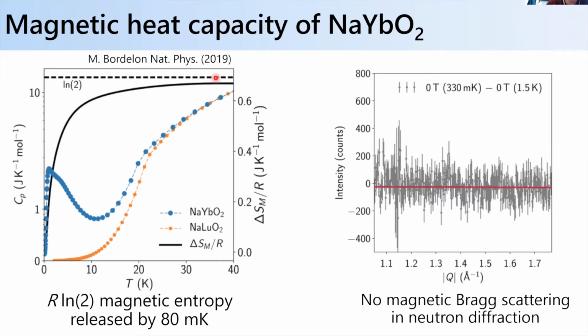So this tells you two things. First is that the J effective 1/2 model is correct in this temperature regime. And the second thing is that by the time you've gotten down to 50 millikelvin, there's not really much entropy left to give, okay? You've sort of frozen the magnetic entropy out. So there's not a hidden, even lower temperature ordering transition that we should expect.